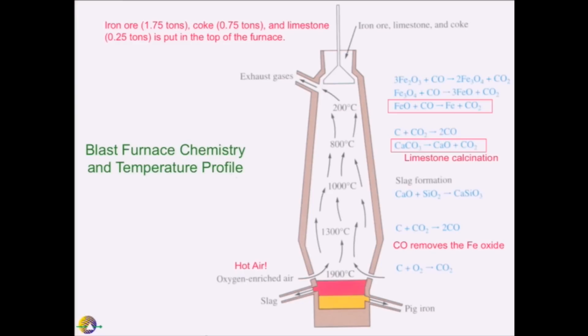It's going to react to form carbon dioxide. The solid carbon fuel interacts with the oxygen to form carbon dioxide here at the bottom, right? And this is where the blast furnace is the hottest. As you move up, it gets cooler. It also has less oxygen. So it's a reductive environment up here and an oxidative environment down here. Carbon dioxide is going to interact with more solid carbon that comes into the top to produce carbon monoxide. Carbon monoxide is a strong reducing agent. And it interacts with our iron oxide, our somewhat pure iron pellets coming in at the top.